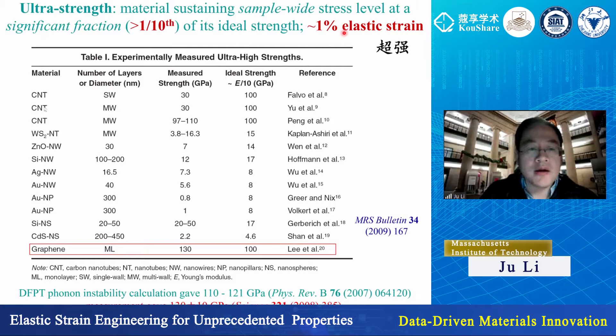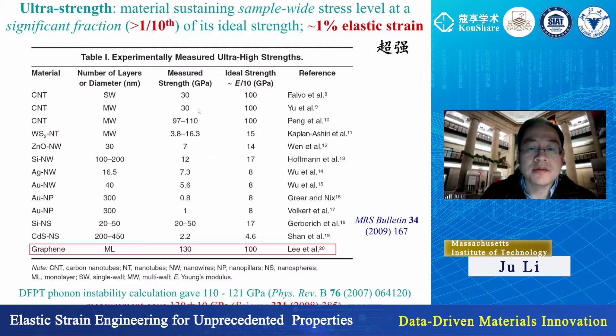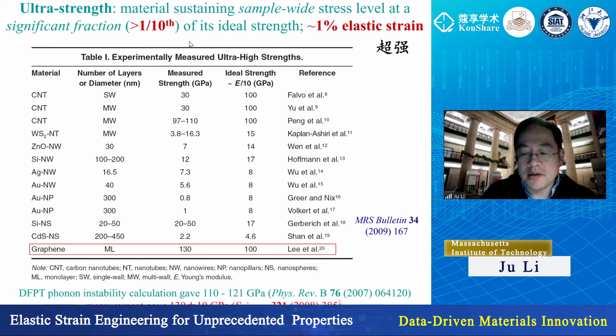Here is some experimental data for carbon nanotubes, nanowires, nanoparticles, nanospheres, and graphene. One column shows one-tenth of the Young's modulus; the other shows measured strength. You can get a significant fraction, sometimes really approaching the theoretical strength. One extreme example is graphene — the thinnest possible in one dimension. In 2007, we calculated the ideal strength to be 110 to 120 gigapascal, and a year later there was a measurement of 130 gigapascal.